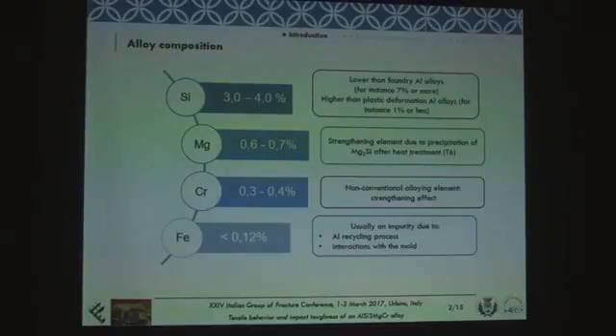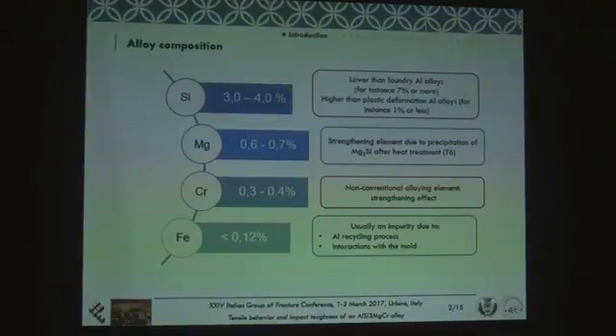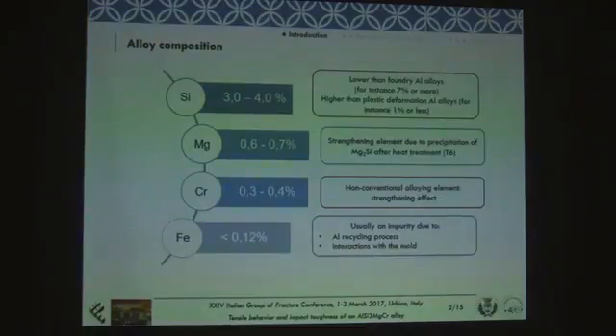And this is the first, let's say, non-conventional aspect of this material. Magnesium is also present as a main alloying element, and chromium between 0.3 and 0.4% was added to the chemical composition. Finally, it is also important to consider the iron present, which is usually an impurity in this kind of alloy, but which can strongly affect the microstructure and the mechanical properties of this material.